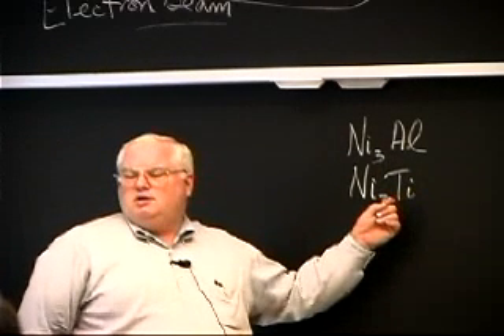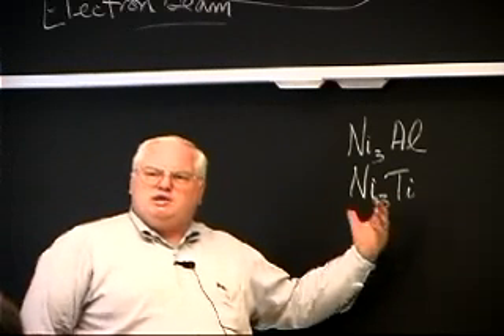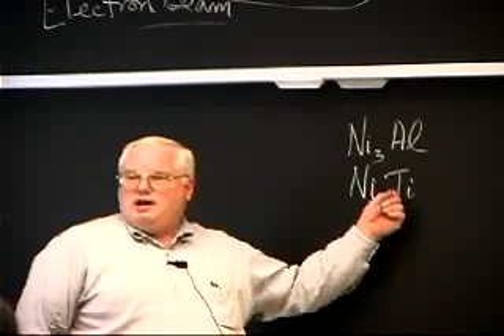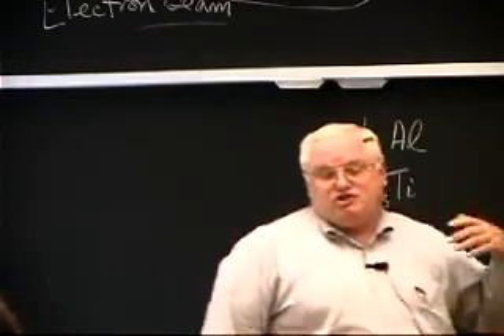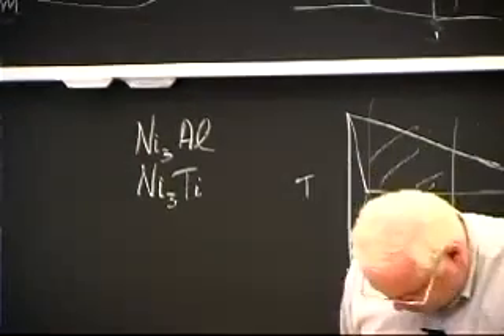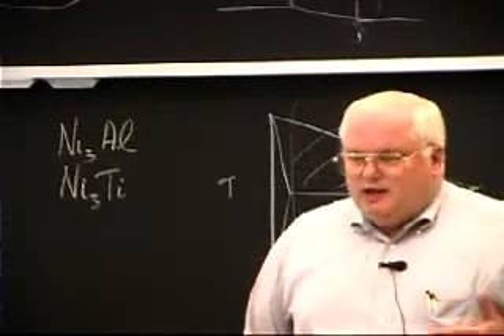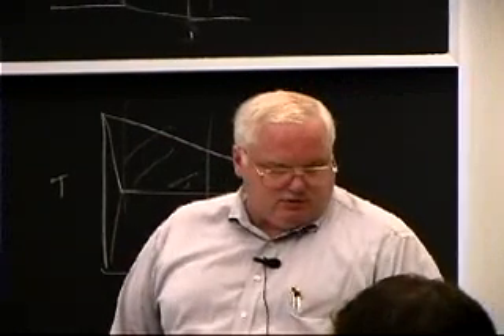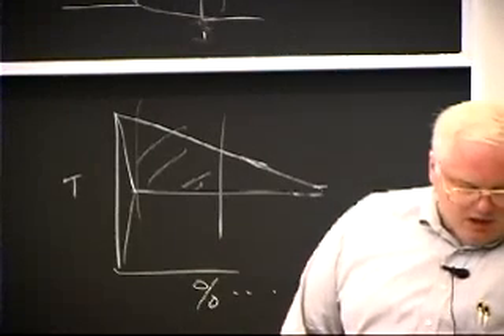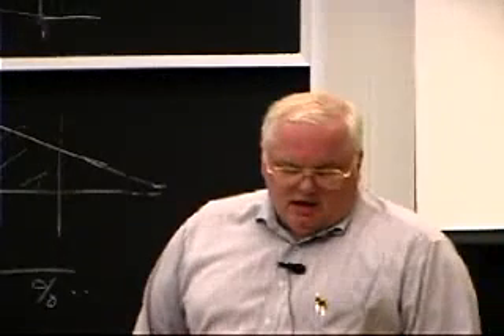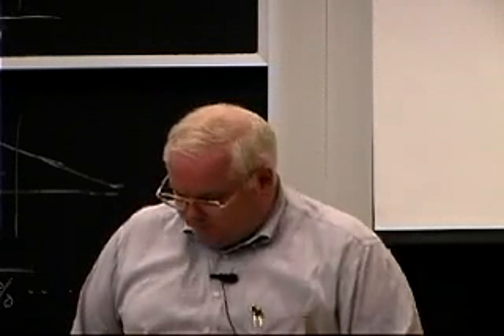Not quite as good high temperature properties, but the weldable high temperature alloys like Inconel 718 have titanium replacing some of the aluminum. There are actually some alloys where they completely replace it. Can't remember which ones they are right now. But in general, it's just sort of a trade-off between the aluminum and the titanium and the weldability. They can be welded. A lot of research has gone into their weldability, mostly because you're talking very high value added parts. A turbine blade can be worth $4,000 and you screw it up and you can't repair it after you've tried to repair it improperly, then you've got problems. But you really can weld most of these things.